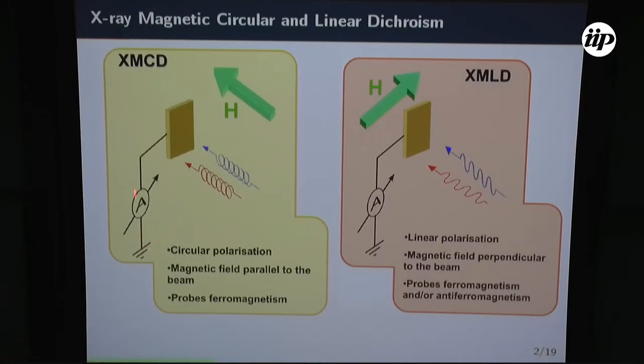A parenthesis here. You see the amperemeter connected to this sample. This represents the way we measure the absorption signal. Because the X-ray doesn't transmit through the sample, you have an indirect way of measuring the absorption. Normally, when you have the absorption phenomena, you have a decay that produces lots of electrons to the vacuum, and then you charge your sample. The moment you charge your sample, if it's a conductor, from the ground you have electrons coming up to balance this charge, and you can measure those electrons. This current is proportional to the absorption to a great extent, okay?